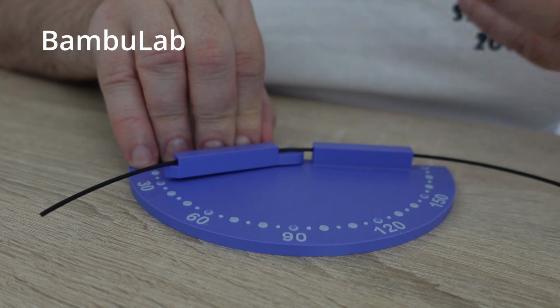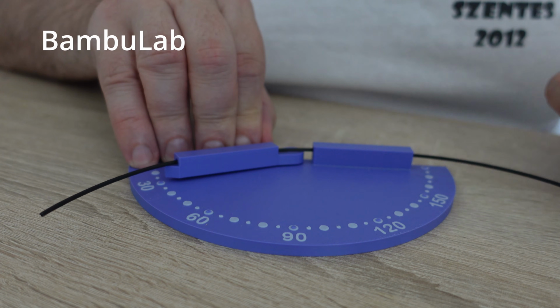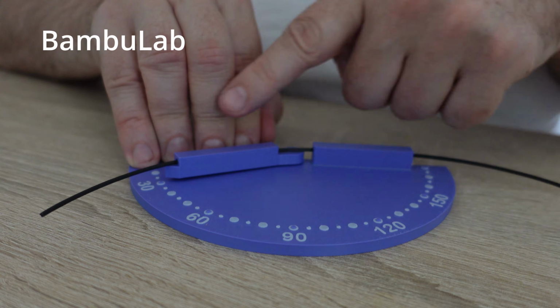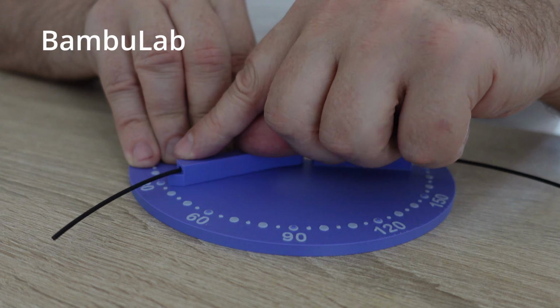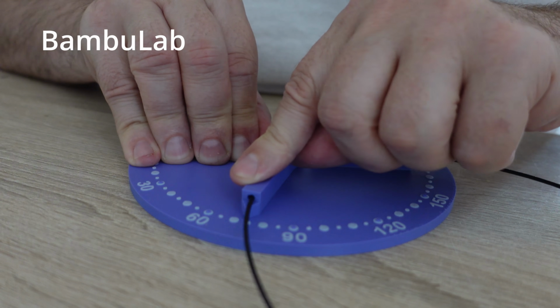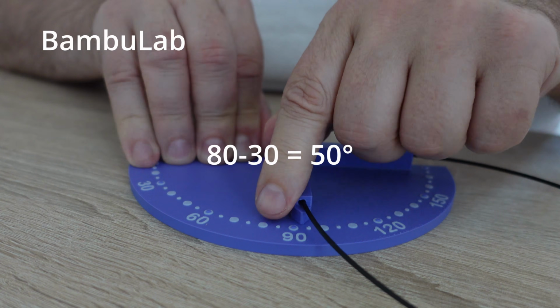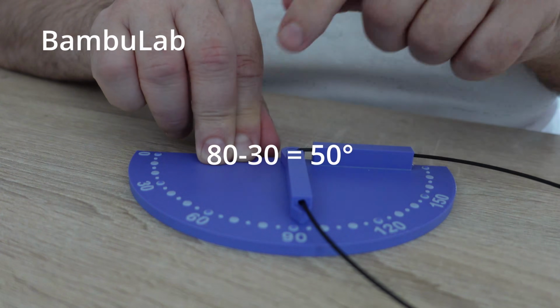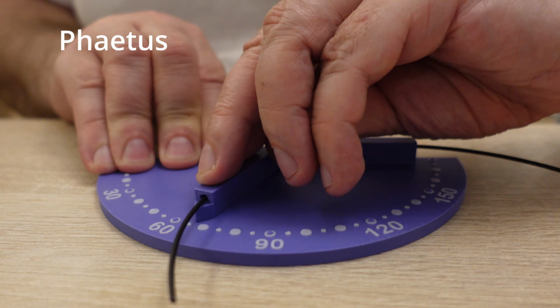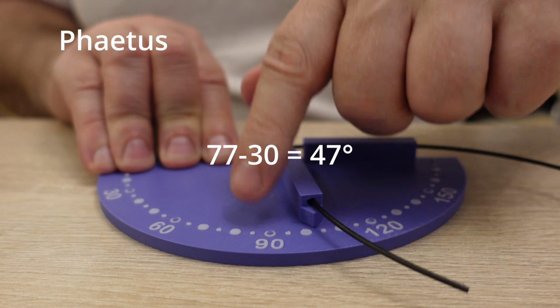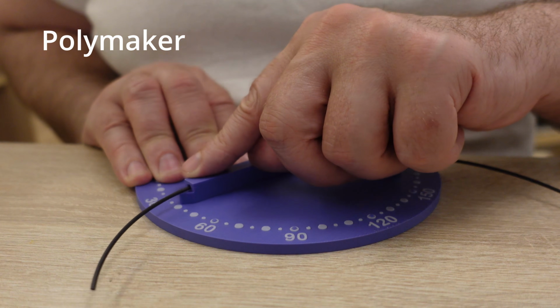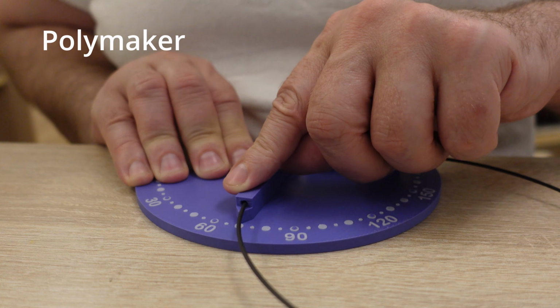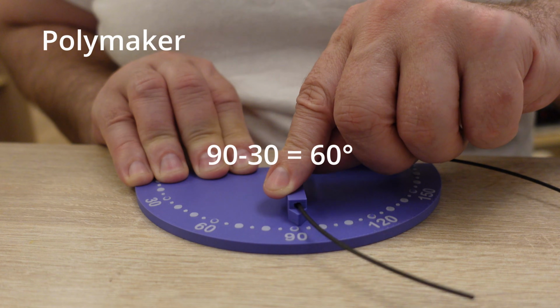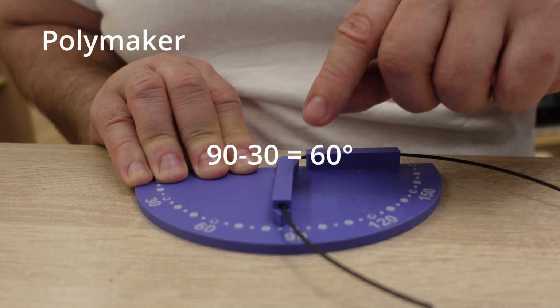Filament bending test immediately after the drying, but I was waiting until it cools down. This is BambuLab, start angle 30 degrees. Maybe 80, but I will check the footage. This is Phaetus, and in every case I was waiting 15 minutes after I took it out from the dryer to cool down. Polymaker Fiberon. The most flexible so far.